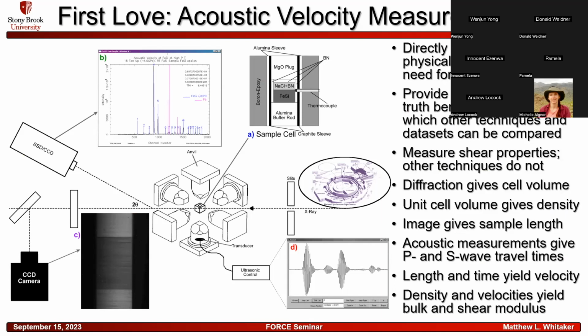The diffraction that we collect gives us the unit cell volume. The unit cell volume is a direct measure of the density of the sample at all of the conditions of pressure and temperature. The X-radiographic image of the sample gives us the sample length at all of those conditions. And the acoustic measurements that we make using ultrasonic interferometry give us the P and S wave travel times. When we have the length and the time, that yields the velocities, which means that the density and velocities yield the bulk and shear modulus, which we then have directly measured at every condition of pressure and temperature without the need for fitting, which is super cool.